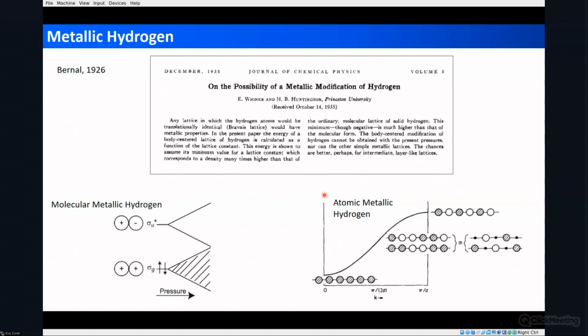Another example of metallic hydrogen could be atomic metallic hydrogen, and this is exemplified by the one-dimensional chain that Julia was studying, where if you have an equal distance between all of the hydrogen atoms in this chain, you end up getting a band structure that is the epitome of a one-dimensional metal. And of course, we don't see this at 1 atmosphere because you get dimerization, the formation of H2, and because of that, the opening of a gap, as in molecular hydrogen. So pressure is going to be able to enhance metallization, either by this band broadening or potentially by stabilizing this type of atomic metallic hydrogen state.